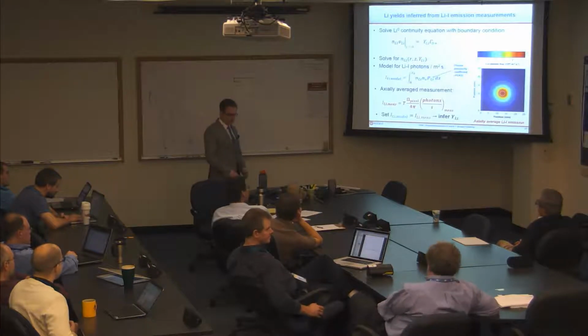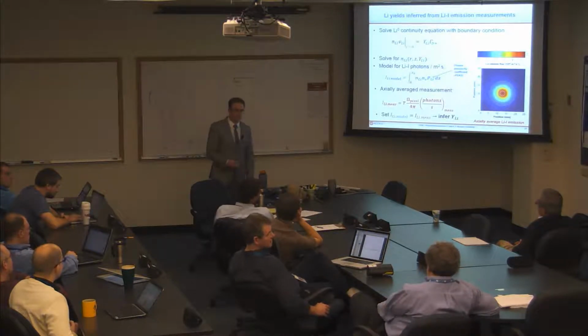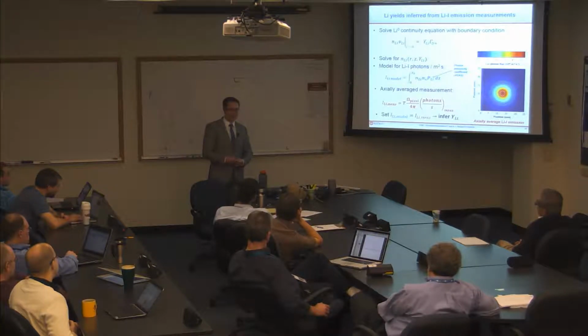If you did this with the melt motion ones, were they more chaotic looking? Yeah, a lot more chaotic looking. And generally, the liquid pool in the center tended to be a pretty uniform temperature. So you actually saw a pretty constant emission rate from the middle centimeter squared of the sample.